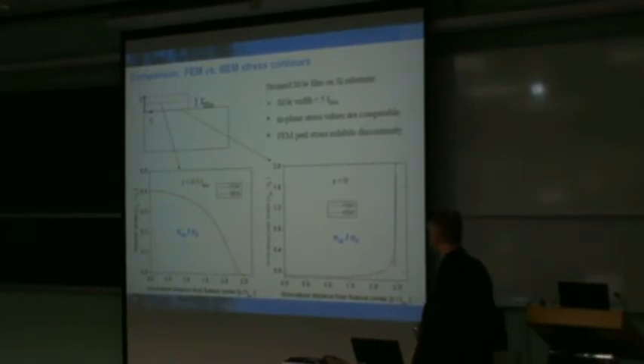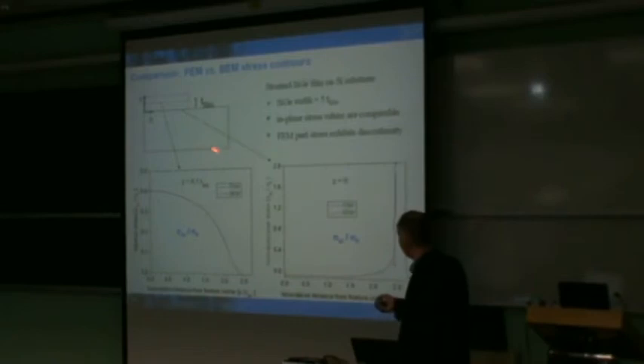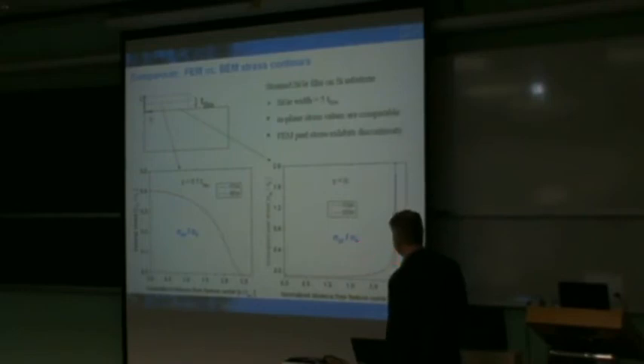Okay. So what I'll show here is a quick example of the contours. The nice thing, again, is that both of these are linear elastic based, and so they should give very similar answers. And so by looking at a contour that runs through the mid-plane of a feature, let's assume our feature has an aspect ratio of 1 to 5 or so, you can see that the normal stress in both cases collapse under the same curve, so that's good. Where the boundary element method really sees an advantage is as we start to look at those interfaces, and particularly as we get close to that corner region, the singularities are much better incorporated by the integral solution that the boundary element possesses. And so by looking at the out-of-plane stress that's here, normalized by the driving force, we can incorporate these singularities in a much more tractable nature than the finite element method.